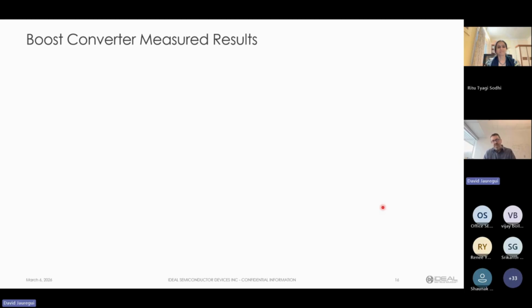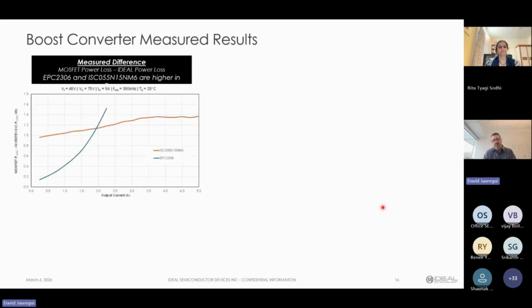What happens when you actually measure it? Well, here are the measured results. This is delta power loss versus current. So again, looking at their power loss minus us. And so as expected, the Infineon at light load behaved as we expected it. And then when you got to full load, the difference in power loss approached what we expected. What we did not expect is what happened with the GaN. At light load, it was all EOSS related losses, which made sense, and we were supposed to have an advantage.